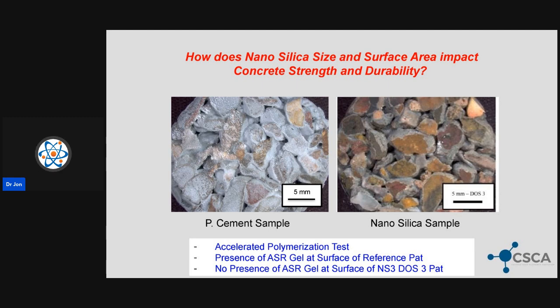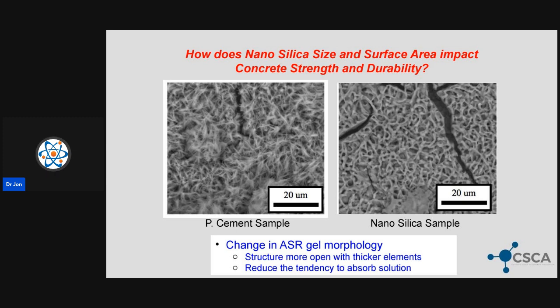The image on the right is that same type of sample, but now we've put in dose 3 of our larger colloidal silica, our CS3, the 45 to 47 nanometer. You don't need to be an expert to see that there is a major difference between the amount of gel that we can find on the surface of Portland cement by itself versus the amount when we used the nano silica on the right. There's almost none present. Now, when we look a little bit deeper into the ASR gel morphology, the rosettes, if you will, not only do we see a change in the amount of ASR gel, there's a change in the structure, where those wispy-like fibers become thicker elements, changing the diameter of those pores, reducing the tendency for the ASR gel to absorb solution.